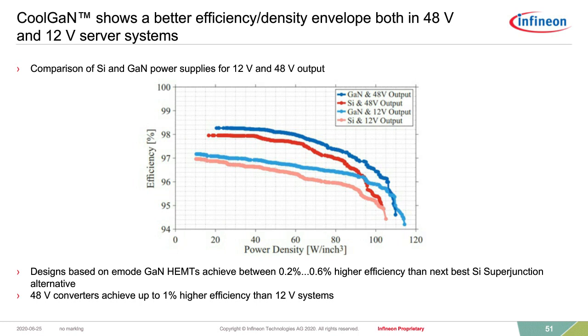We are not talking necessarily about a factor 2 in density. We are talking about 10 to 15 watt per cubic inch better with GaN. So silicon, if used in the proper setup, the right topology, the right control, is not that far off. Therefore, we believe at Infineon that silicon will not just disappear in the market, but will remain in the market for quite a time. So, summing up my talk,